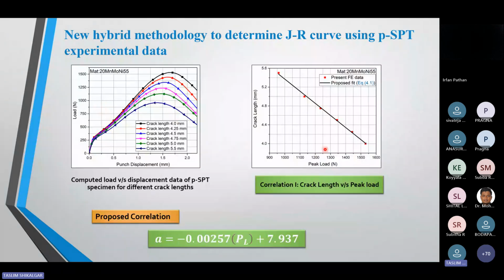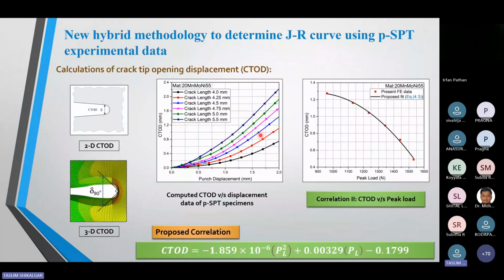If I put in any value, like my numerical peak load is 1500, I get this crack length, but my experimental peak load is less. If I go here, I get the maximum crack length. So with the help of this correlation, you can find how much the crack grew during the test.